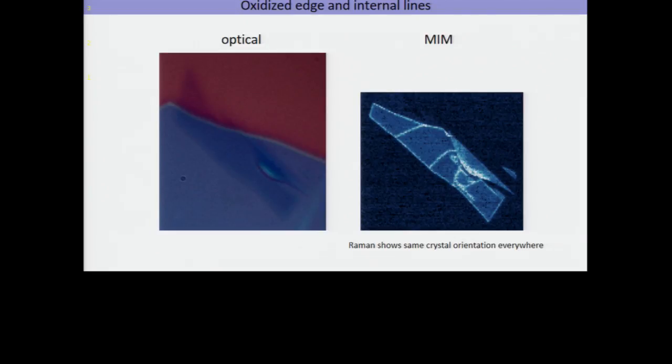But you can see that we always see the internal edges are brighter. The cracks are brighter, I should say. Right? Yeah. Would a dislocation in the plane also give rise to this, if it's not a crack or a separation? Would a dislocation give this effect or not necessarily? A dislocation in 3D is a line, and in 2D it's just a point, right? Yeah, okay. So this has to be a grain boundary or a twinning boundary or something.